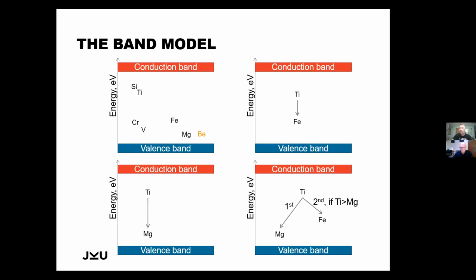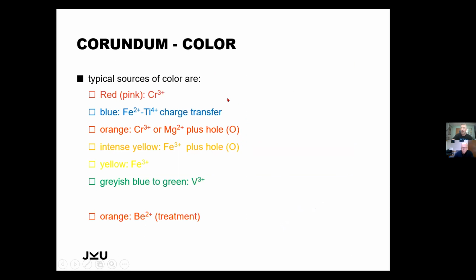And with this, I hope I could explain to you the three most important causes for color, not only for corundum, but for almost all of the minerals that we have. And especially for corundum, we have a couple of elements that we know, which we can 100% assign to color, which is the chromium, for example, the red and the pink color. Chromium needs about 1% to create a ruby. If it's lower, then we talk about pink sapphire.